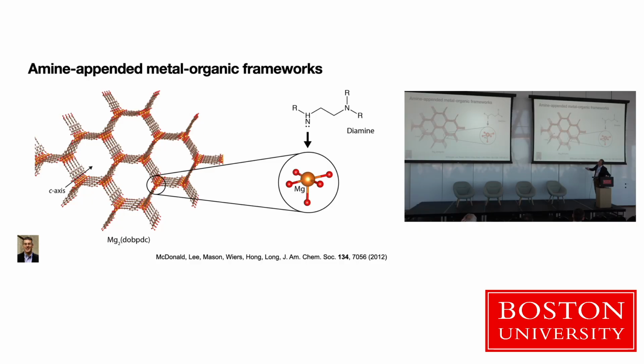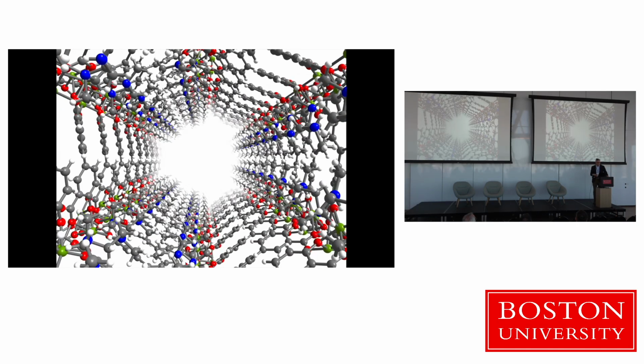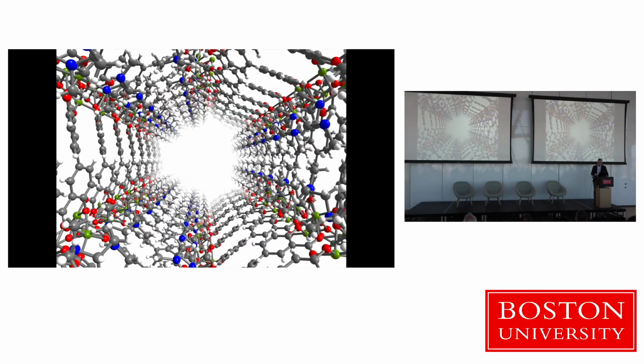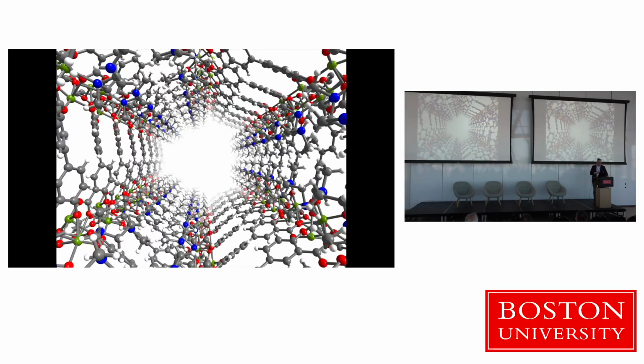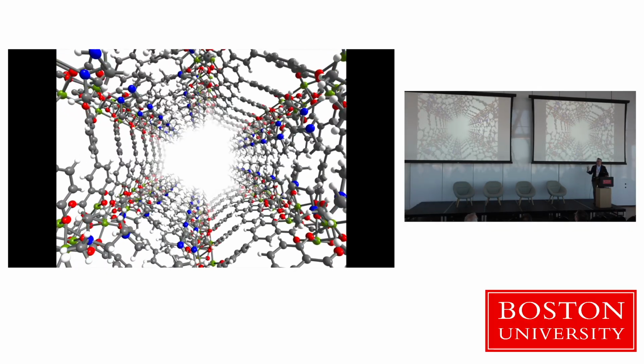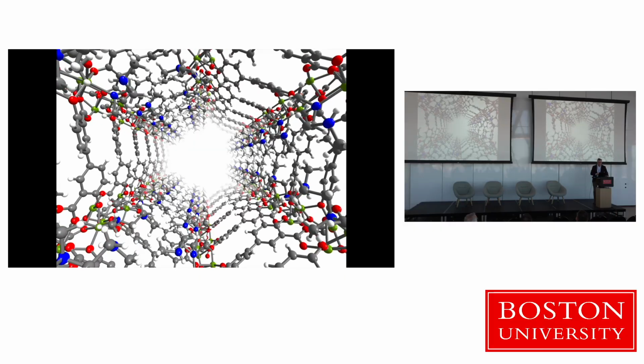So one end of this diamine bonds very strongly to the metal, and then the other one is exposed, and that can react with CO2. And there is a well-known CO2-amine interaction, and in bulk industrial contexts, usually CO2 is captured within amine solution. So there's sort of a precedent for this. So the idea is, this is just a cool movie, but the idea is to append these amine groups to each one of the metal centers.